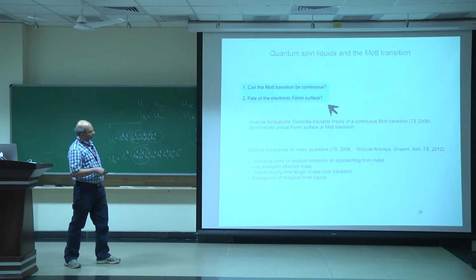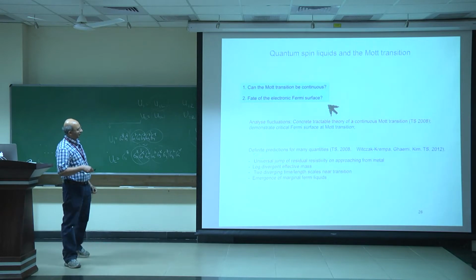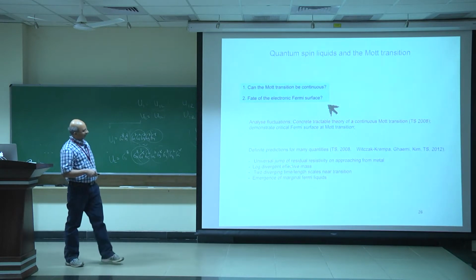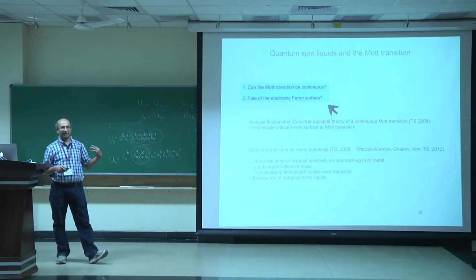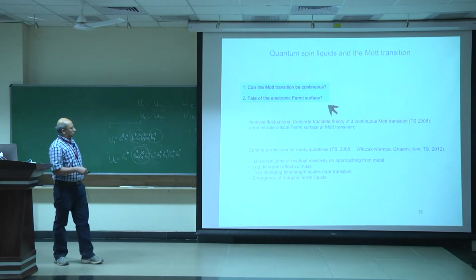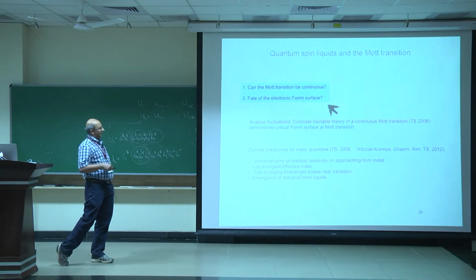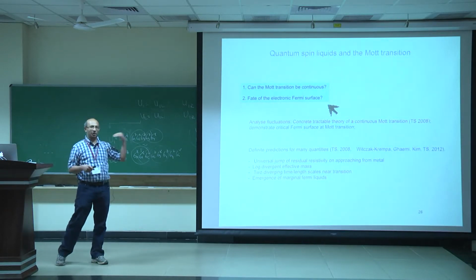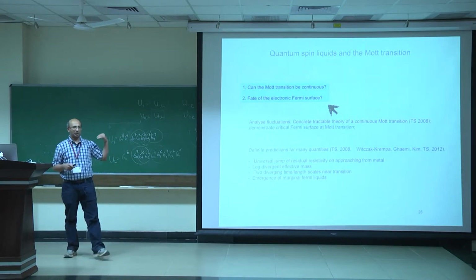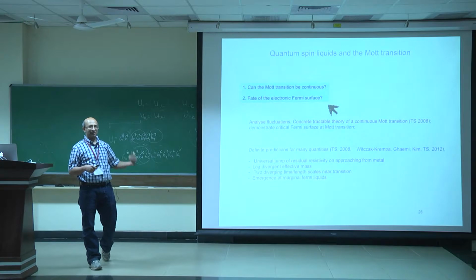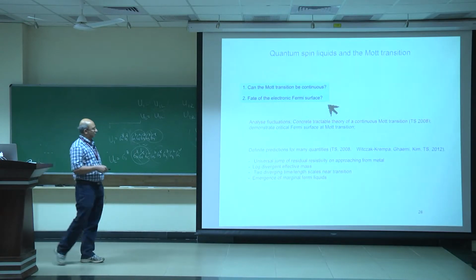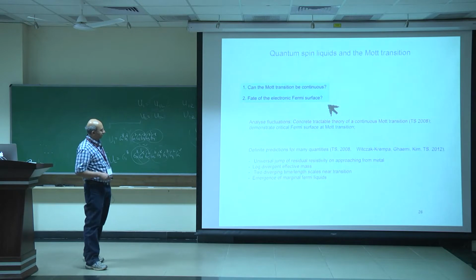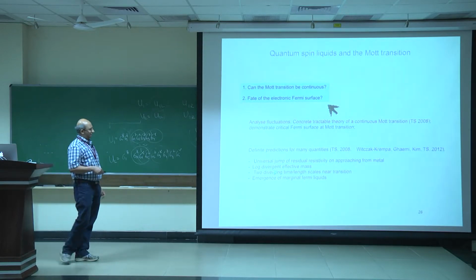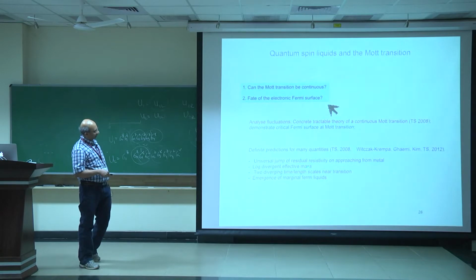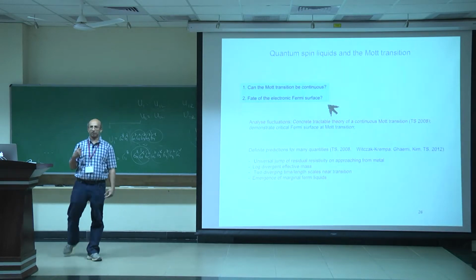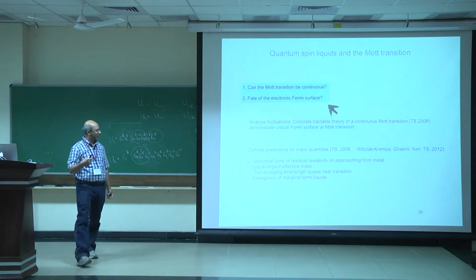One prediction which is probably very pertinent to experiments is that you're going from a metal to an insulator, right? So what happens to transport? What this theory leads to is a prediction that as you approach the transition from the metal, the residual resistivity will show a universal jump of order h over e squared. Right? And in a few slides, I'll show you an estimate of this universal jump of the residual resistivity. Another prediction is that the quasi-particle effective mass in the Fermi liquid will diverge as you approach the Mott transition, but will diverge very weakly, only logarithmically.